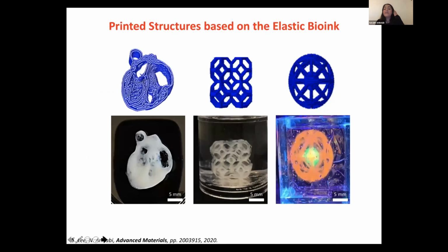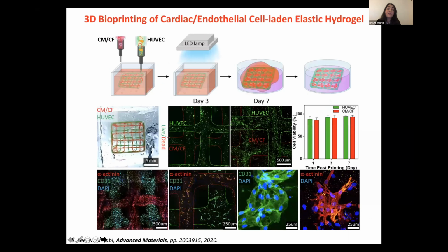So by using this FRESH technique, we can use any type of bioink that has soft mechanical properties. We can form complex structures based on these biomaterials, as you see in these images. So as one example to show that the designed bioinks are biocompatible, we form a multi-layer structure. In one layer, we use a gelatin-based bioink laden with cardiac fibroblasts and cardiomyocytes freshly isolated from rat heart. And for the second layer, we use our second nozzle that was loaded with elastin-based bioink laden with endothelial cells.